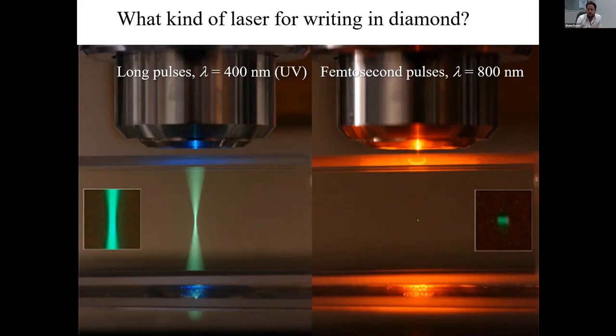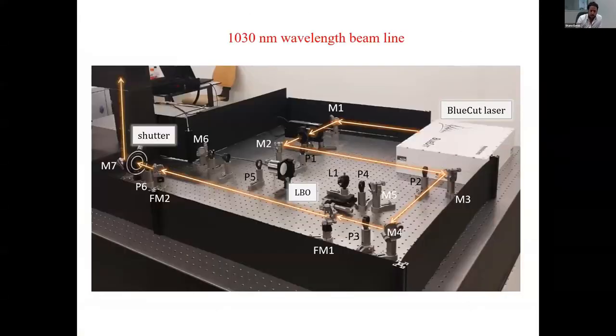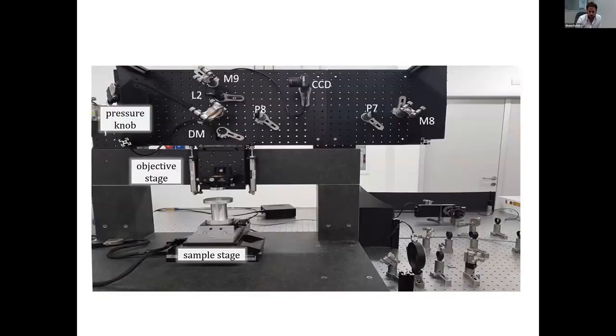So we rely on this multi-photon nonlinear absorption to achieve very pinpoint 3D microfabrication in transparent materials and also in diamond, for example. Here is our laser setup in Lecco. The white box is our femtosecond fiber laser from Menlo, a company in Munich. And essentially, it's quite a simple setup. It's various mirrors guiding our laser towards a final focusing lens. We have the options of using the 1030 nanometer fundamental wavelength, or we can even use the green wavelength, which is more compatible with oil immersion microscope objectives. And so that's typically what we're using.